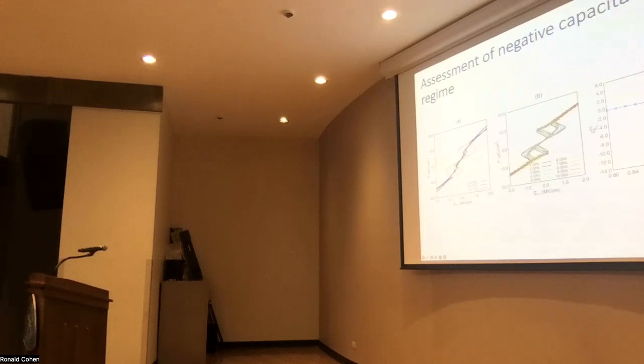So we went ahead and we assessed that negative capacitance regime. We realized that if we are much below Curie temperature, the red data here, we have that very nice negative capacitance regime. As we approach Curie temperature, the blue set of data here, the loop shrinks. And of course, with that, we have less and less of negative capacitance regime region. And finally, as we are above the Curie point, there is no loop, there is no negative capacitance regime for us.